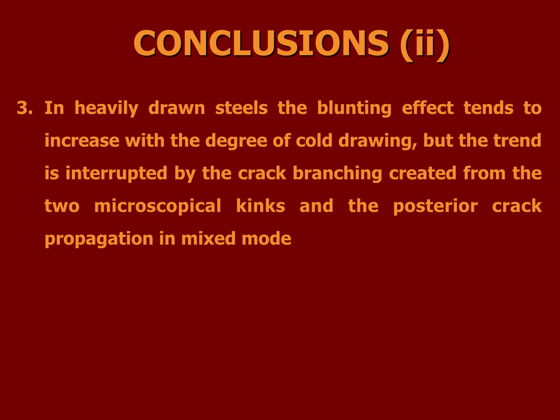In heavily drawn steels, the blunting effect tends to increase with the degree of cold drawing, but the trend is interrupted by the crack branches created from the two microscopical kinks and the posterior crack propagation in mixed mode. And that's all.